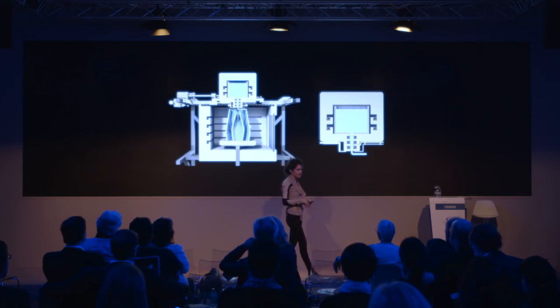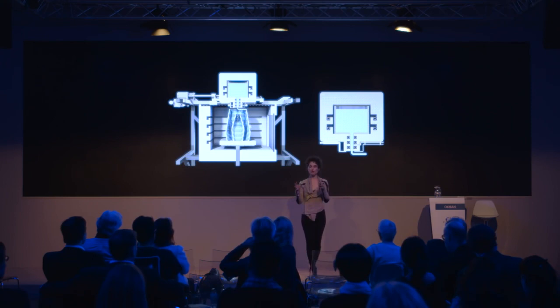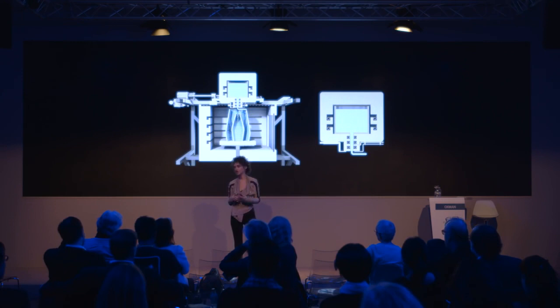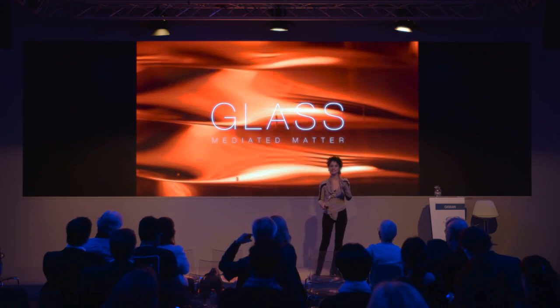This printer was designed and architected from scratch in my lab — a collaboration between Mediated Matter, the Glass Lab at MIT, and the Mechanical Engineering department at MIT. The printer has a kiln cartridge that allows us to take in molten glass and control the gradient of temperature, thereby controlling the viscosity of the glass, and thereby controlling the geometry of the deposition. It has a crucible kiln and a kiln around the nozzle with thermocouples that allow us to control the variation of temperature as we control viscosity. Let's play the video.